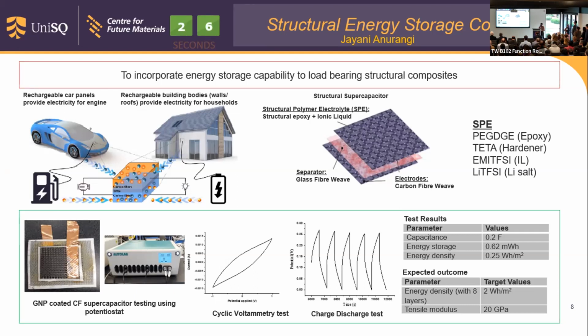So in my research, the main focus was the structural energy supercapacitor functional structural composite, because it has a laminated structure. When I developed the electrode, I used graphene-coated carbon fiber layers. After fabricating the structural supercapacitor, I evaluated the electrochemical properties. According to my results, I calculated that around 2 watt-hours per square meter of energy can be stored in my